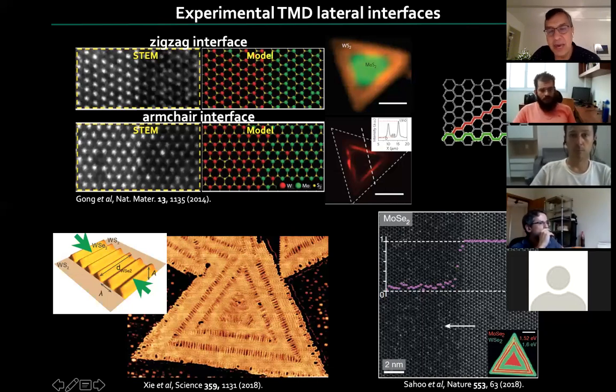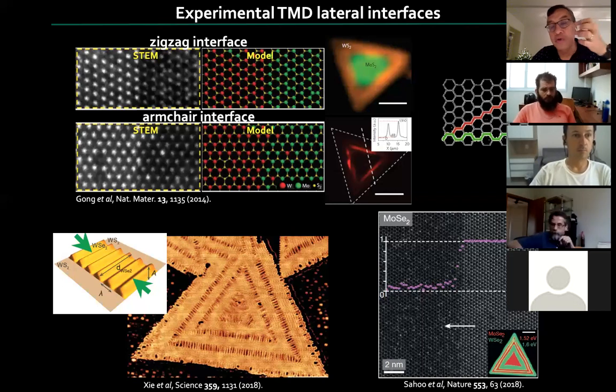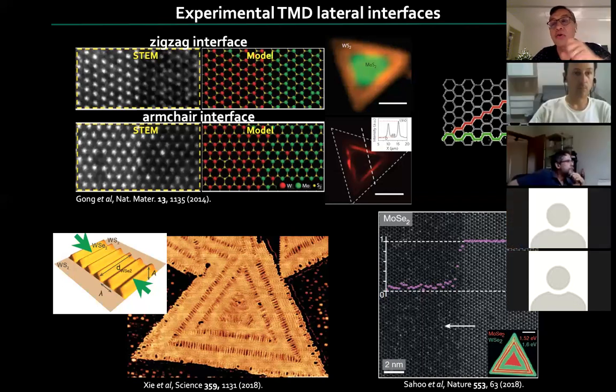Now, we're saying the chalcogen matters for the lattice constant. In what you see here on the left, it's tungsten, the same metal, but they're changing from sulfur to selenium. So by changing the chalcogen, the lattice constant changes dramatically. The strain is much larger, to the extent that the layer that grows in between grows like an accordion. So by changing composition, you'd be able to control the strain. And there's Park's group in Chicago that plays around with these sort of materials. But the point is that it is possible to play around with different interfaces.